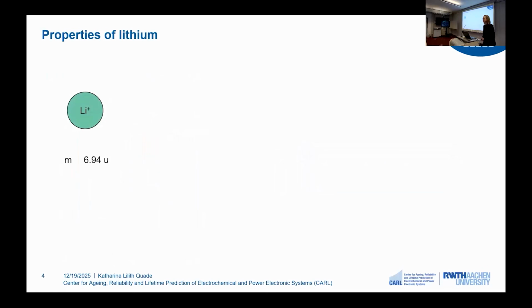But why do we use lithium for batteries in the first place? Lithium is a very light alkali metal, has a small radius, and a very negative reduction potential. And this means, from a purely electrochemical view, that we can achieve high voltages and also high gravimetric energy density. However, lithium is classified as a critical raw material, and we can see its availability is quite low, with only 20 parts per million in the Earth's crust.